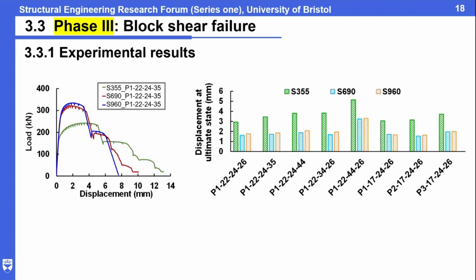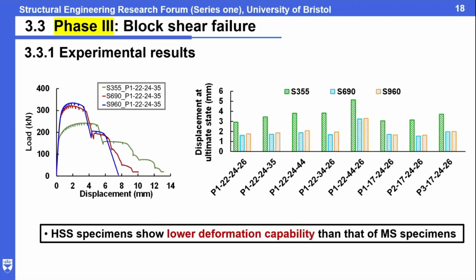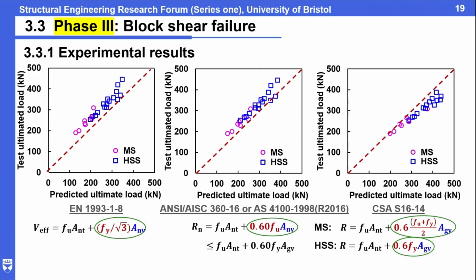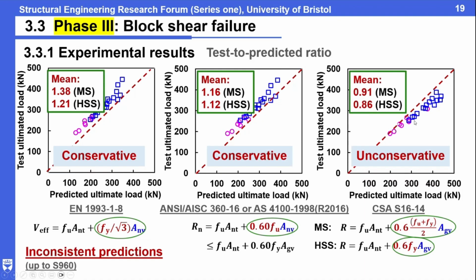And then it goes to phase 3, block shear failure. For block shear failure, this is a normal way to compare ductility. The key part is that we have mentioned the design codes provide inconsistent design equations, right? So we base it on the test data to compare the predicted and tested values. We found that the first one is Eurocode, followed by the American code, and this is Canada. The Eurocode is conservative, with each ratio above 1. The American code is conservative still, but the Canadian one is unconservative.